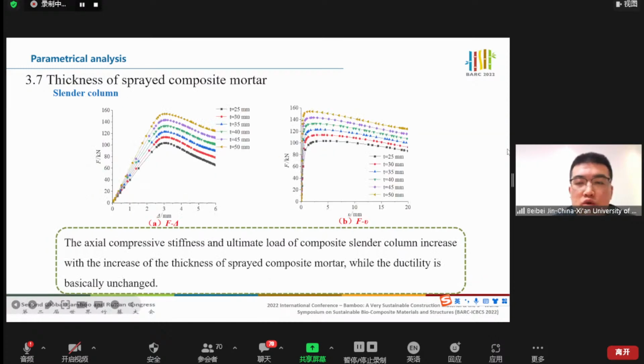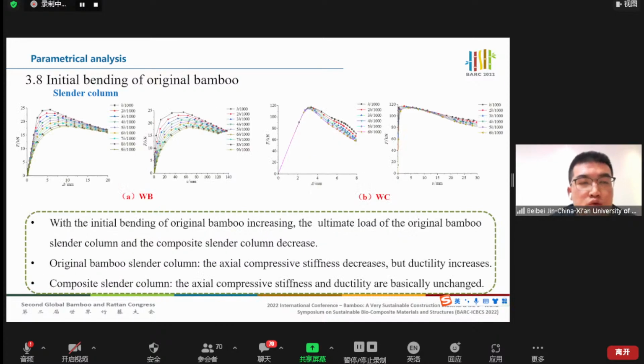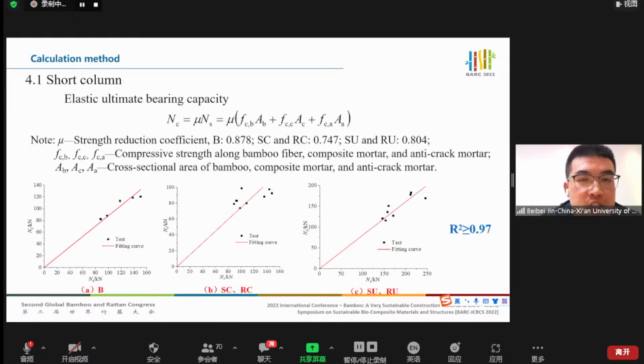And also the thickness of the sprayed composite mortar layer. For the slender column, the axial compressive stiffness and ultimate load of the composite slender column increase with the thickness of the sprayed composite mortar, but the ductility is basically unchanged. This one is the initial bending of the original bamboo for the slender column. With the initial bending increasing, the ultimate load of the original bamboo slender column and the composite slender column decrease. For the original bamboo slender column, the axial compressive stiffness decreases, but ductility increases. For the composite slender column, the axial compressive stiffness and the ductility are basically unchanged.